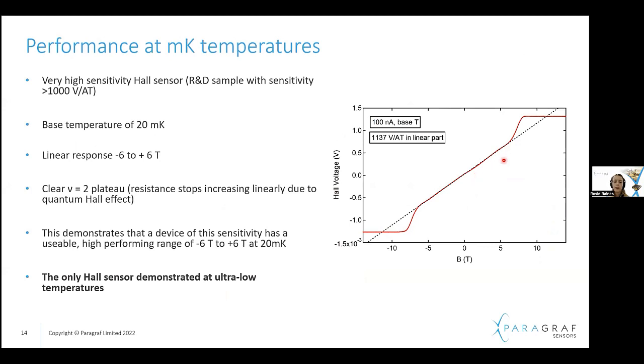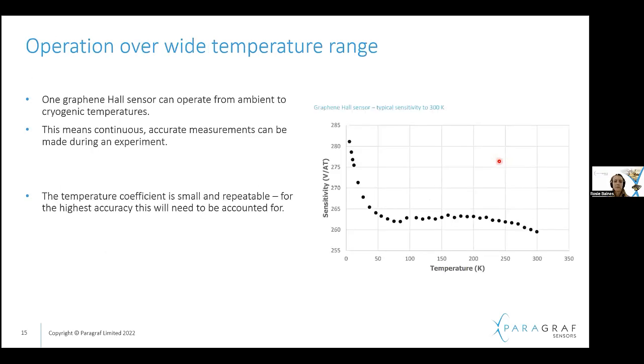So this is a really exciting result. This is the only Hall sensor demonstrated at these kind of ultra low temperatures. And within this range, you can see it's a really clear linear response. So this is a really interesting result here. However, it's not just the cryogenic temperatures.